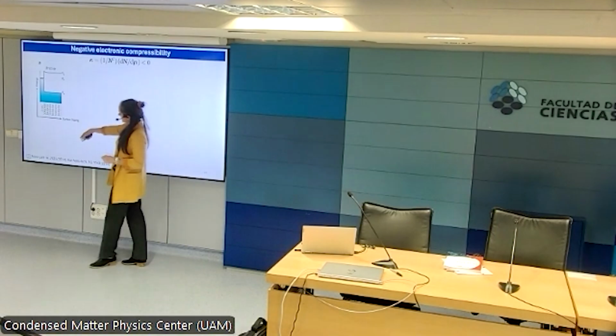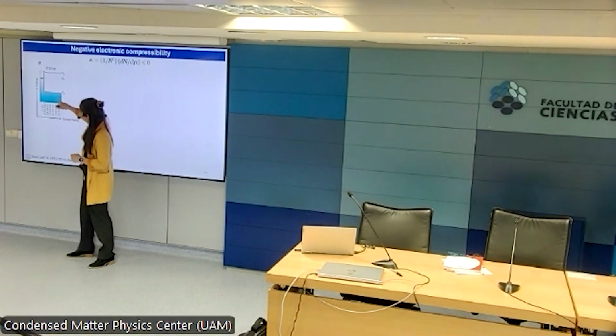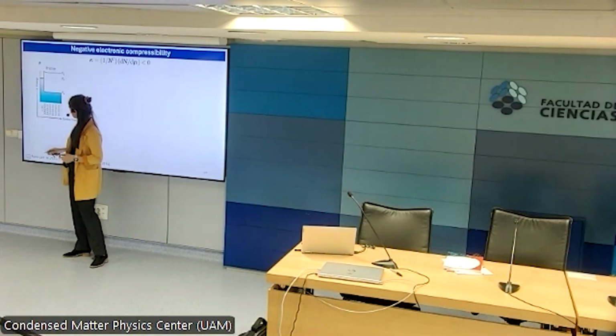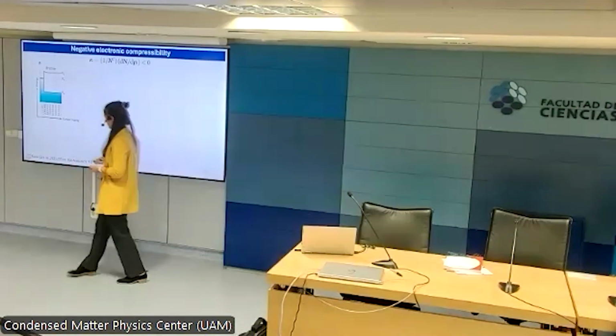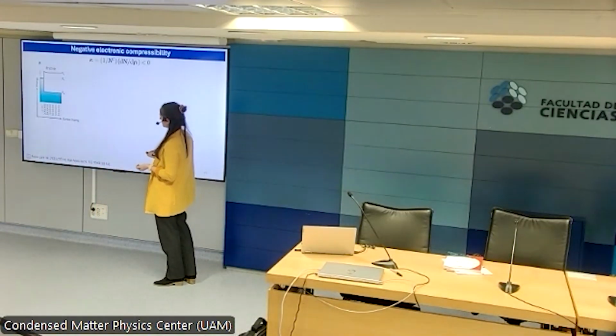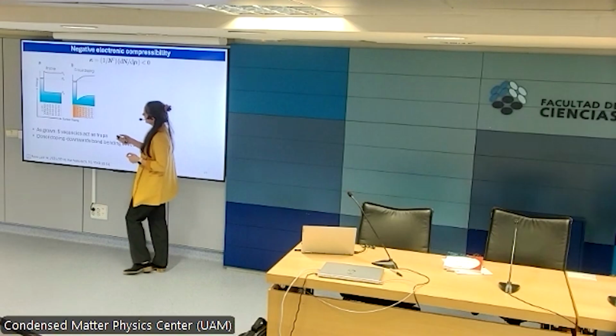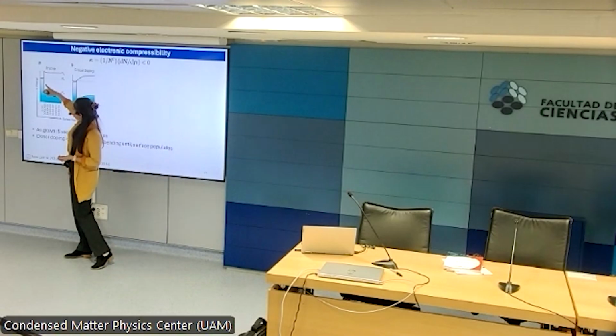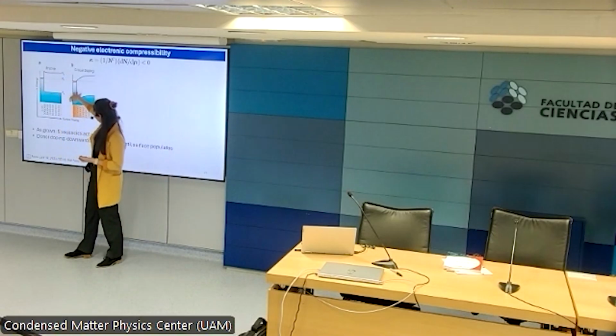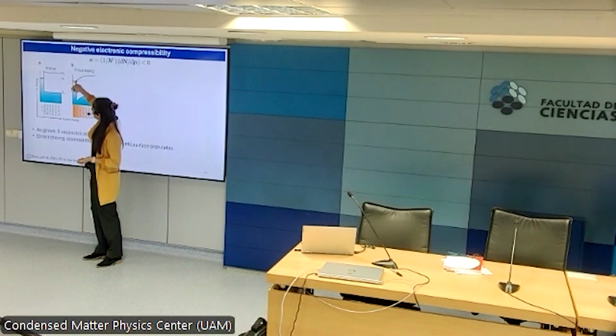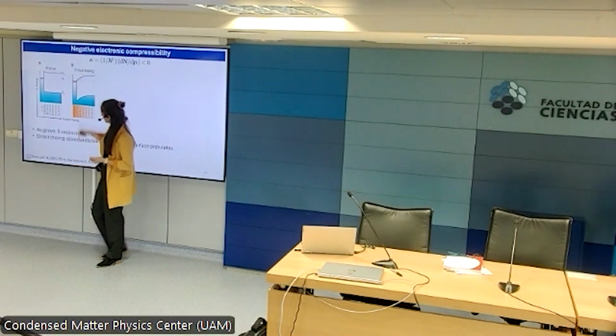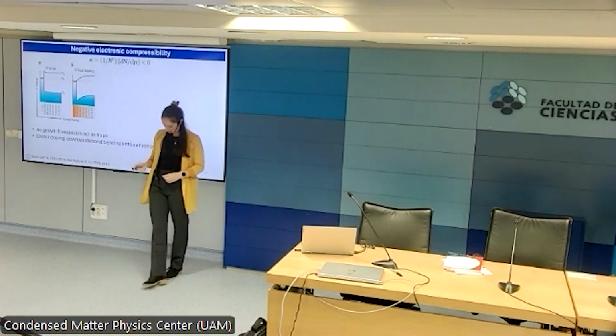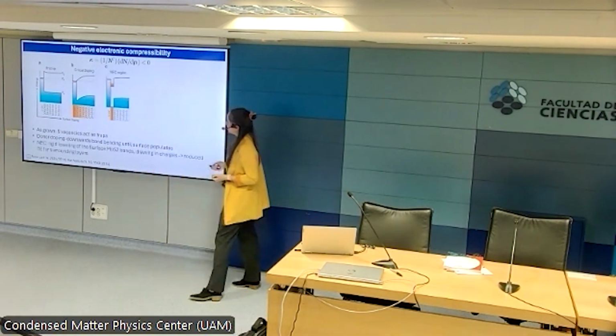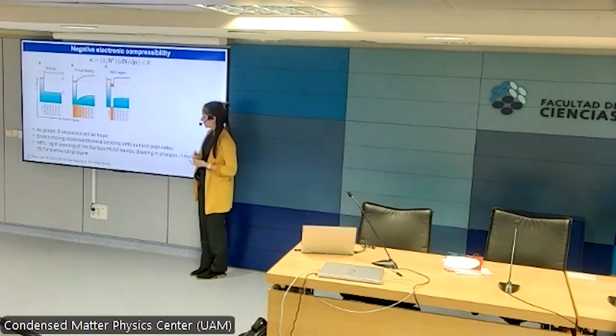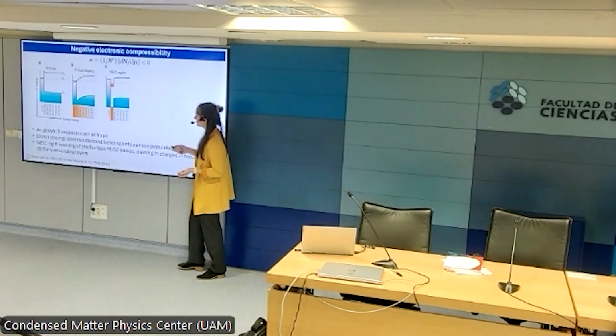This is the system as we build it. You can see that there's a very small upward band bending of the states of molybdenum disulfide because of sulfur vacancies on the surface. We start putting electrons. You can see that both systems shift downwards with respect to the Fermi level. The band gap of tungsten ditelluride goes fully down, and then there's a strong band bending of MoS2 downwards until we hit a critical doping for which the negative electronic compressibility regime has its onset.